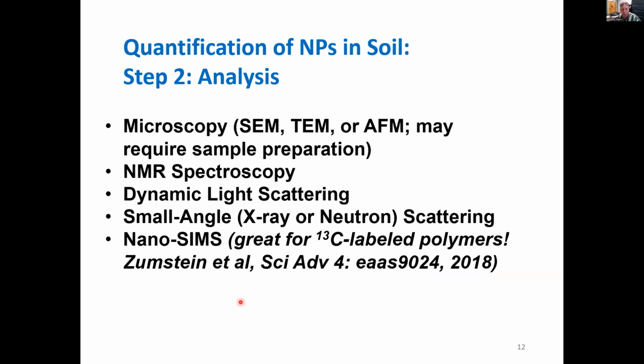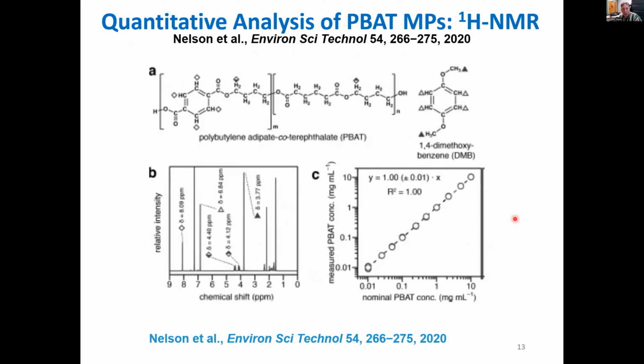And then also on the experimental side, a great technique is secondary ion mass spec, which requires, though, a radio-labeled polymer to do that work. Here's just a quick example from the literature involving NMR. This is of PBAT, and these are microplastics. There are specific signatures in the NMR spectrum for the different monomeric units of PBAT. For instance, these aromatic protons over here at 8 are very easily detected for the terephthalic acid monomeric unit.